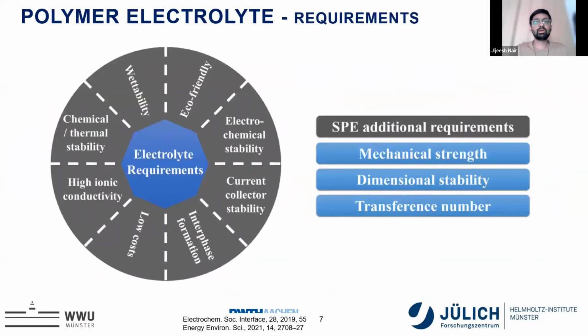So from the polymer electrolyte point of view, what are the requirements we have? What are the requirements of a material, for example? Whatever the properties that we have from liquid electrolyte, we want that. For example, wettability, eco-friendliness, electrochemical stability, current collector stability, high ionic conductivity, low cost, etc. In addition, you also need mechanical strength, dimensional stability, and higher transference number because the conductivity in a solid state system is comparatively lower. And the higher transference number can also reduce the polarization at the interface.